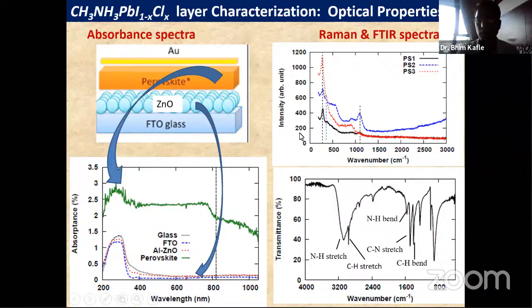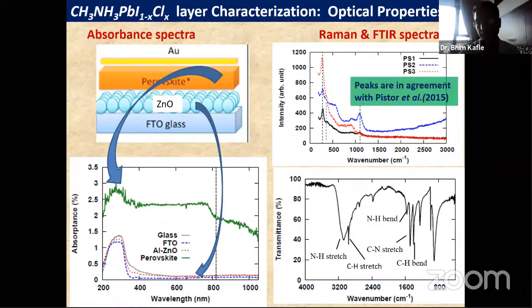These are Raman spectra, and these peaks corroborate well with other papers. Also, the appearance of functional groups, NH stretching, NH bending, and the presence of CH bending peaks in the IR spectra also confirm the indication of a nitrogen-containing or carbon-containing compound. That is what we are dealing with here: the perovskite contains, as I said, carbon, nitrogen, and hydrogen, and also lead, but we cannot see that in the signature.